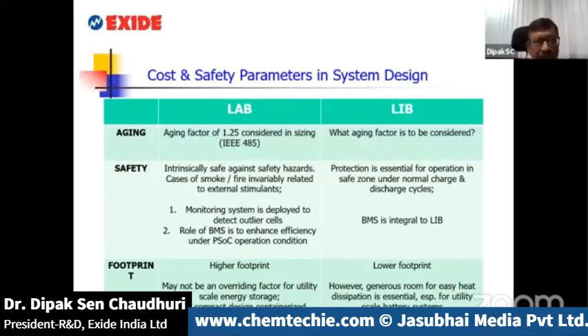Now, whenever we are doing sizing of a lead acid battery, we have a pretty standard aging factor, which is as per the international guidelines, even standardized in IEEE. Whenever we are sizing a particular battery for a particular load, we use an aging factor of 1.25. In lithium ion battery, this is something which is not as yet standardized. So this is somewhere we would like to address user forums like you to push the manufacturers to come into a common base.